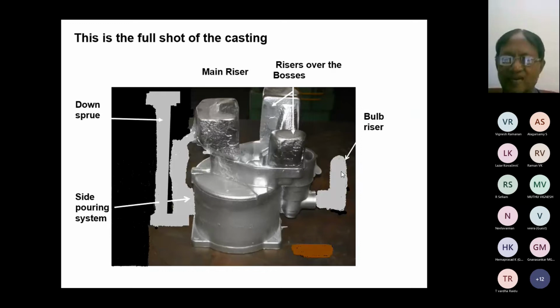Here the die was made, and we tried to make the casting, and this is the casting that came out of the die. See, so much of risers. This is a down sprue, which is coming down nearly about 120 mm, and then the metal enters this one and goes to the top, and it tries to fill. See, by the time the metal goes another 100, about 220 mm, the material will be very, very cold here. See, there is no graying seen at all. It is so solid like a biscuit. It is not at all feeding from this one. This is one bulb riser.